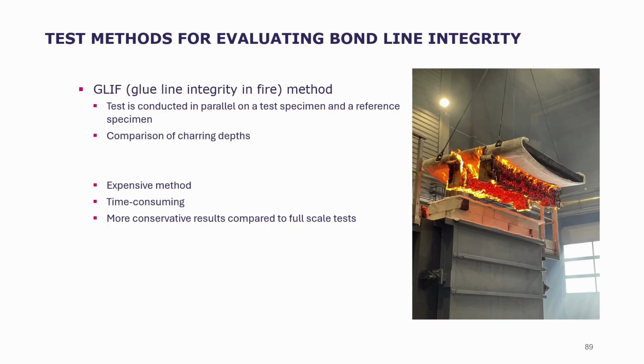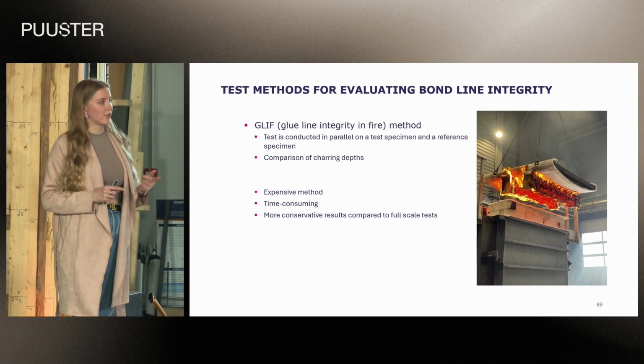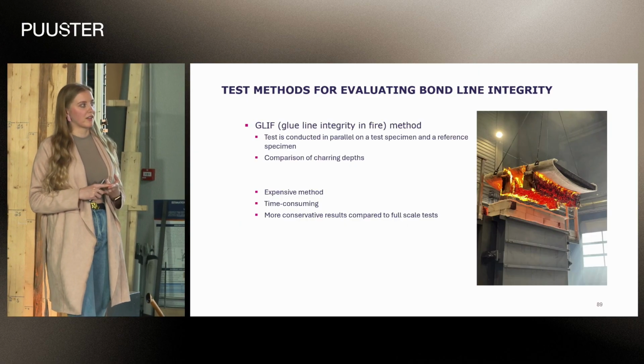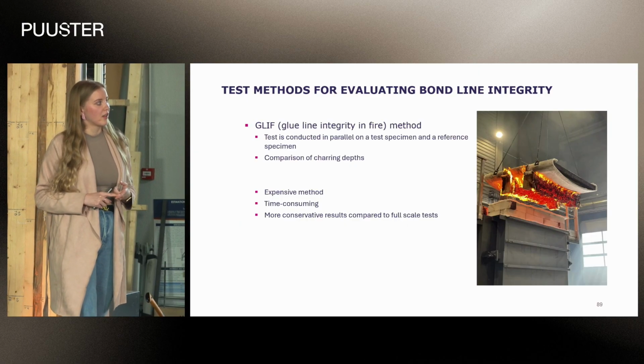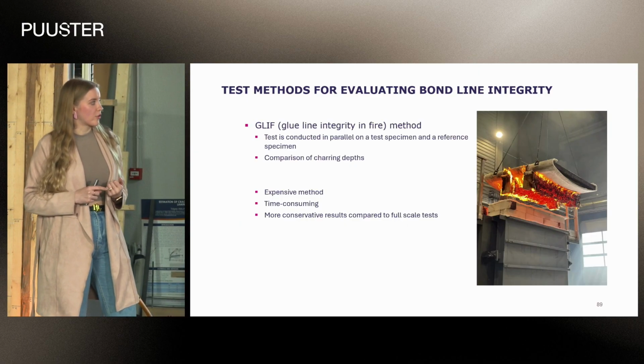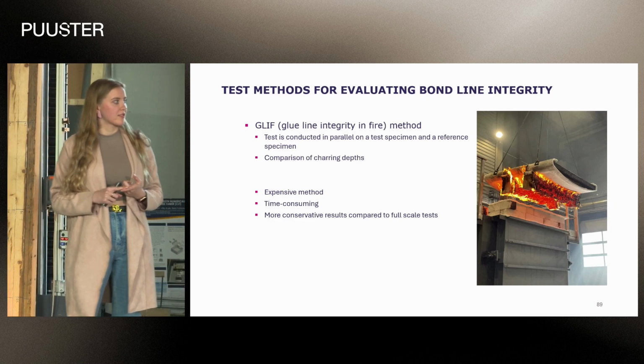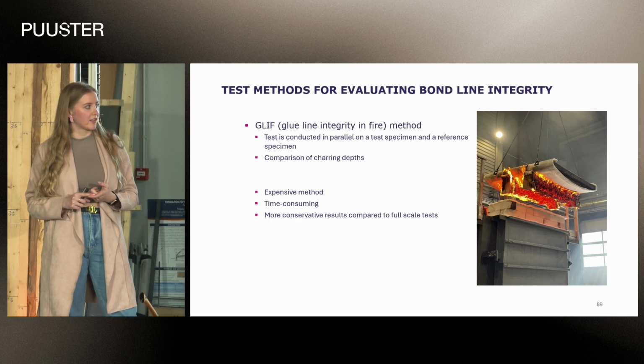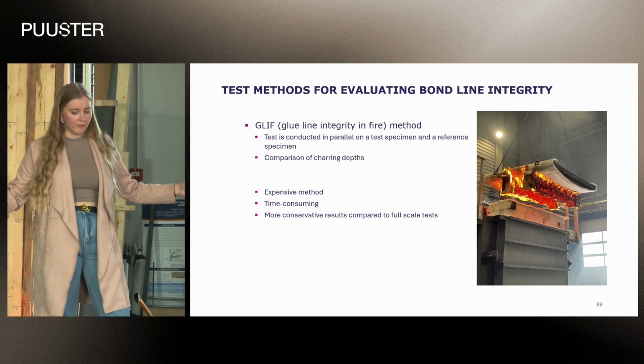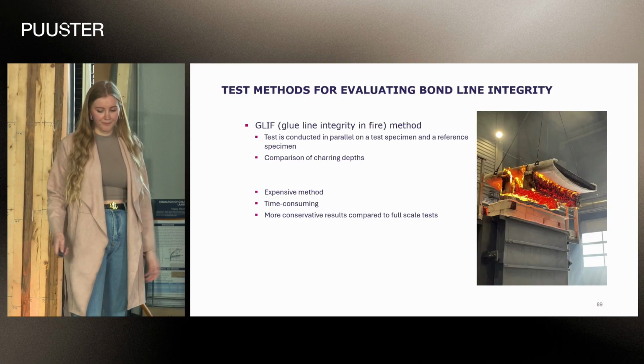Also still pretty expensive, I would say. One test can go up to 5 figures. It's also time consuming, needs a lot of materials, but we do have more test results from these tests compared to the large-scale tests. The results are more conservative compared to the full-scale tests, which is not actually a bad thing, because we can apply the results more widely.